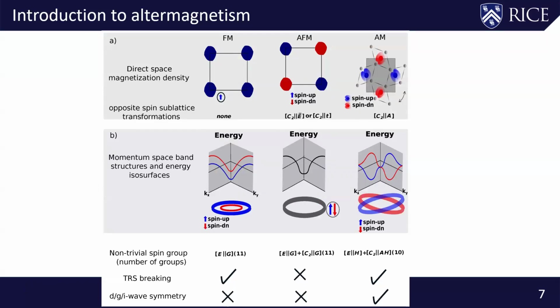So now let me tell you a little bit about what is really expected to be different. As I mentioned earlier, in the case of a simple ferromagnet, you should expect the electronic band to be split, with the spin band having up and down states, and time reversal symmetry is broken. In the case of a simple strictly collinear antiferromagnet, your electronic and spin wave bands should be degenerate, and you shouldn't have time reversal symmetry breaking.